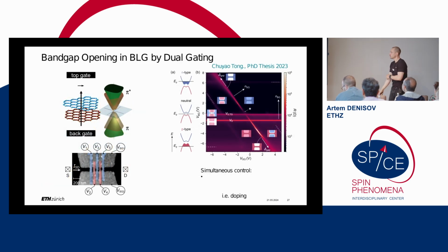Okay, so a quantum dot is a zero-dimensional object. Of course, in order to make it zero-dimensional, you should start with a one-dimensional channel, which we form here by means of a so-called dual gating technique, where we apply voltage not only to the global backgate, but also to these two huge split gates. Our goal here is to open a gap under the split gates, and not only open the gap, but also put a Fermi level inside the gap in order to form a 1D channel.